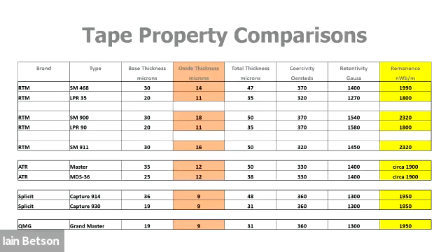But it's still an indication of when people talk about a hot tape as to how much level you can push onto the tape. And one of the reasons you can do that, jumping back to our oxide thickness, 18 microns, is it's an extremely thick oxide thickness for the tape, and therefore you can push a lot of level onto it. LPR90 is a formulation that RTM have created themselves. Agfa never created a long play 900, and all they've done there is taken the same formulation but cut the oxide thickness down by 7 microns.